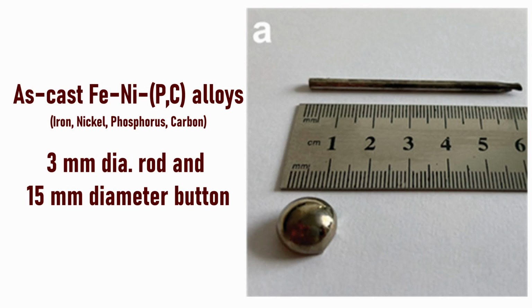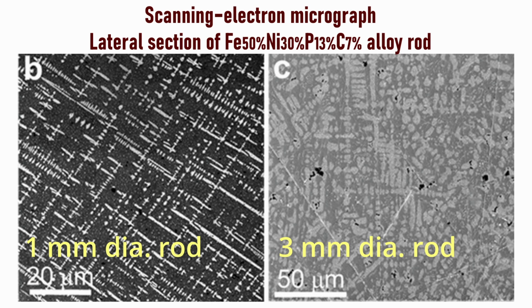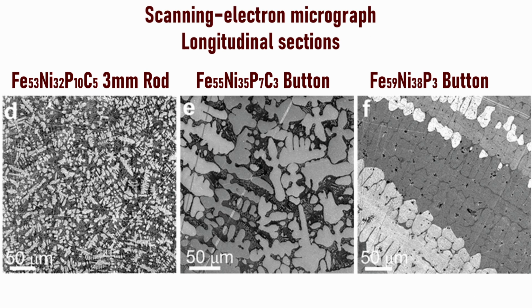In this picture, we see a rod and a button, cast of an iron, nickel, phosphorus, and carbon alloy. Checking the rod with a scanning electron microscope reveals tetrataenite dendrites made of ordered iron and nickel in a carbon and phosphorus matrix. These pictures show results with different ratios of iron, nickel, phosphorus, and carbon. In all cases, electron diffraction shows that the dendrites are indeed L10 ordered tetrataenite.